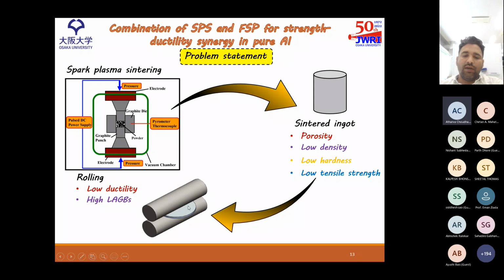So what happens with the rolling? When we do the rolling, the density is 100%, but again the ductility is reduced, and the microstructure consists of a high fraction of low angle grain boundaries. So the ductility is severely compromised.